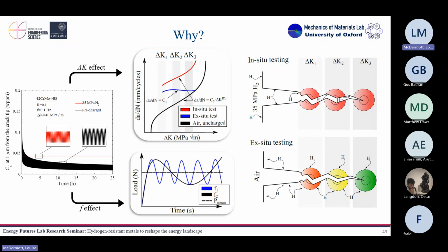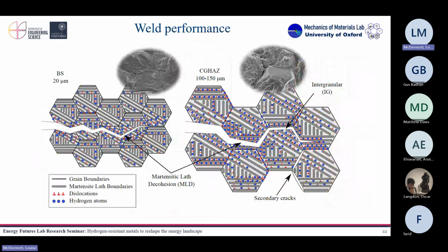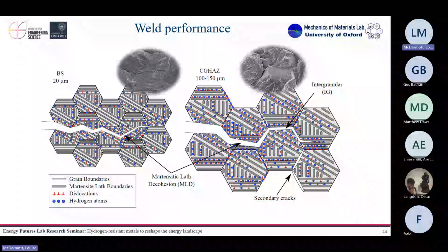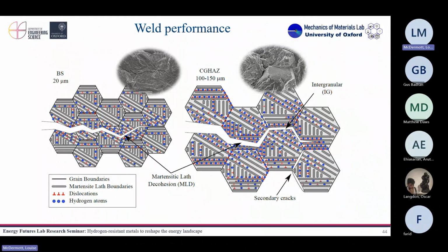So we found out that those were the reasons why we were having that difference of behavior between both experimental methods. And then the last thing we wanted to explain was why the area close to the weld was behaving so badly compared to the area far from the weld. We discovered that the zone close to the weld had a grain size that was massive, and actually you can see the grains are very big, while here the grain was much finer. So what happens, and they both had the same hydrogen concentrations, and they were tested in the same conditions. So what happens if you have the same hydrogen in a grain size that's much smaller?